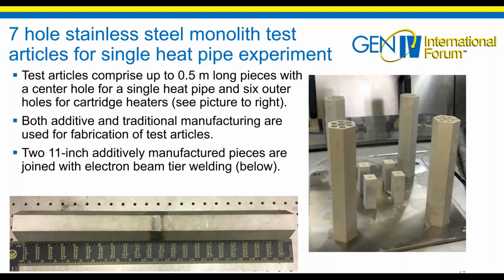11-inch long additively manufactured parts are shown to the right, and they have been joined together using electron beam welding as shown in the picture at the bottom. These articles were fabricated with a laser additive manufacturing technique, a powder bed technique. And we did several different renditions of these to be able to understand the straightness of the holes, how it tapers a little bit from the plate up to the very top, and then the methods that we can use to correct for that and come up with test articles that meet very low tolerances and will be used to produce data on a single heat pipe that we can use to help validate codes that we're developing through various programs.